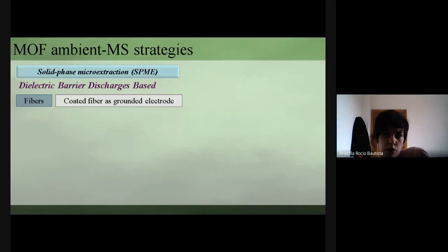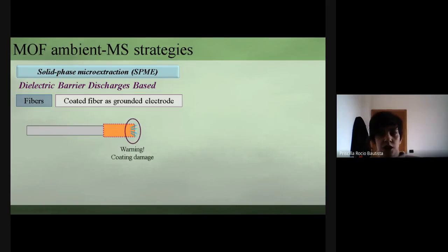Another configuration proposed the use of a coated fiber as the grounded electrode in a low temperature plasma configuration. A metal support, in this case with mainly conductive characteristics, is coated with a MOF and used as the electrode. This is the common configuration of fiber coating at the end of the wire. However, we think that the high voltage reached at the end of the fiber can damage the MOF coating and reduce the fiber reusability. Therefore, we propose to coat the support not at the end, but slightly towards the center.